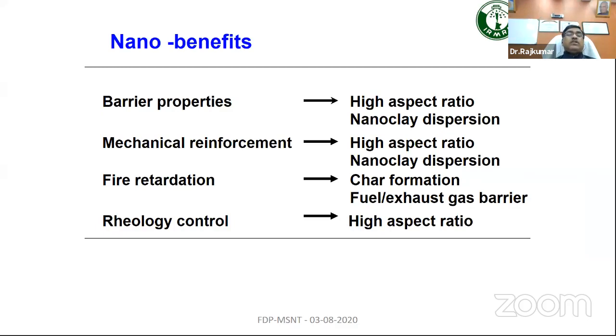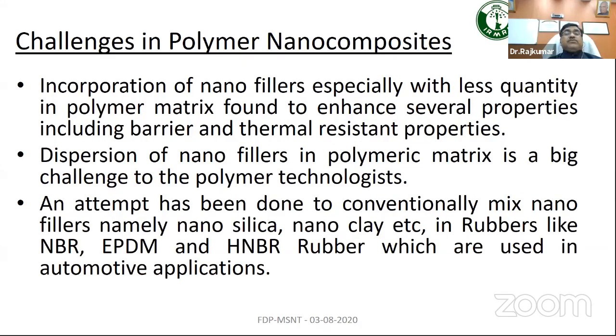This also gives good barrier properties, high aspect ratio, mechanical reinforcement, flame retardance, rheological control, everything is perfect. There's no problem. So with incorporation of nanofillers, especially in very, very minor quantities, we found that they enhance several properties, including barrier properties and thermal resistance properties. But the dispersion of such nanofillers in the polymer matrix is a big challenge for polymer technologists.